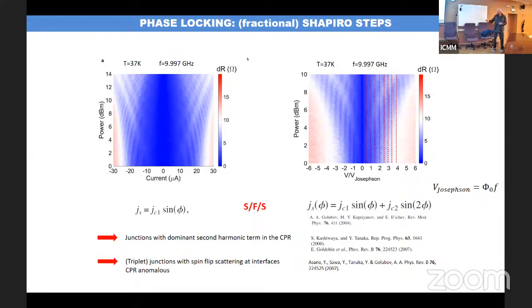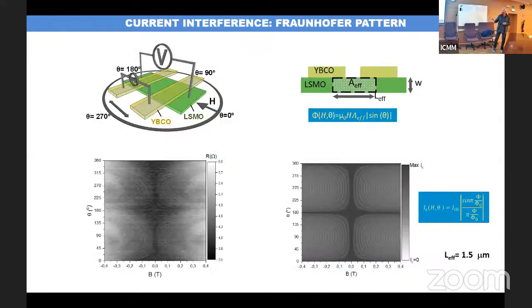But now, if we realize that there is a dominating second harmonic, if we go back to the interpretation of the Fraunhofer pattern, and we admit that there is a doubling of the periodicity due to the dominating second harmonic, the effective length that we get is instead 1.5 micrometers, which makes a lot of sense physically, right? Because there is a 1 micron separation, and then this length scale is increased by twice the London penetration depth, due to the penetration of the magnetic field under the YBCO electrodes. And these numbers then make a lot of sense, physically.